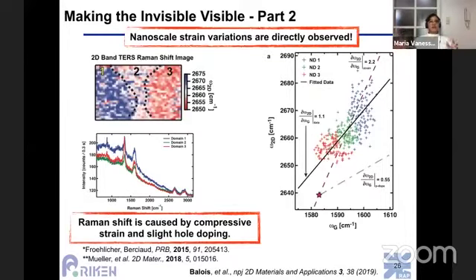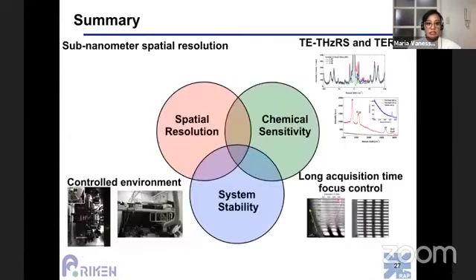And the nice thing about this is, okay, we have a high resolution system. We can also do imaging because we can see the topography. And we found that we can observe these nanoscale strain variations. Note that this image is only 23 nanometers by 14 nanometers in height. These nanoscale strain variations can be directly observed. Previously, they could not be directly observed because of the diffraction limit, and could only be observed via the broadening of certain Raman peaks. But now, using our system, using TERS, we can do such kinds of high resolution imaging and also obtain very small information with high chemical sensitivity.